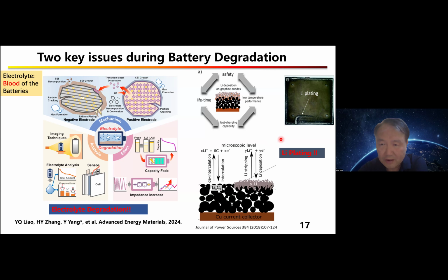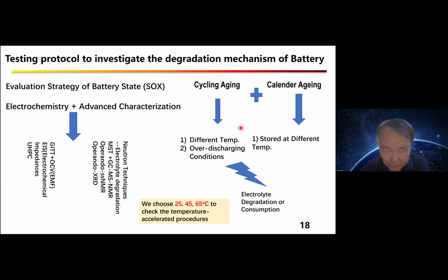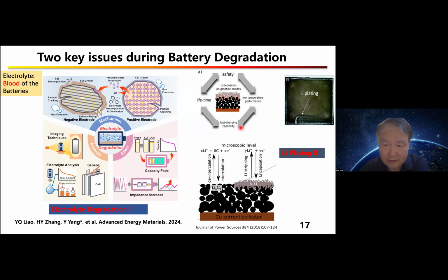And also lithium plating, which always happens when you charge at high rate - it's not only depleting the active material, it also causes some shortage of the battery and safety issues. So these are very important factors we should consider during this research.